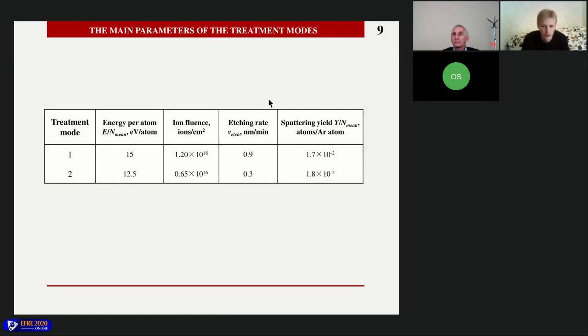On this slide, you can see the main parameters of the treatment modes. Firstly, the treatment modes are not high energy, to cause less subsurface damage during processing. Secondly, the first mode had a high etching rate to more efficiently etch the subsurface damage layer. And the second mode had a low etching rate, but was more efficient.